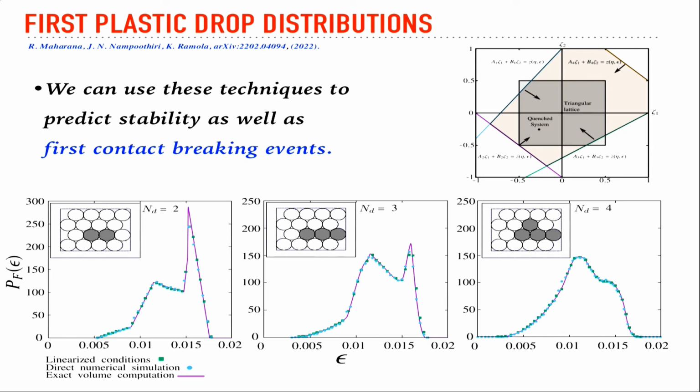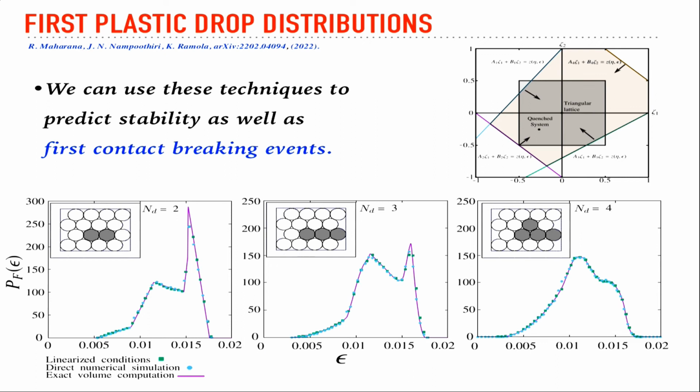As you increase polydispersity, you get a larger distribution here. This is more like some activity in the system, not fracture as such. If I shear a glassy material, things slip. Is this indicative of that, or of the system failing? This does look like a system-spanning event, so it's not a localized event. But it would not be considered a failure in the sense of a fracture. I would expect that as you increase the polydispersity, the distribution of when this fracture occurs would also increase, and the scaling can be extracted from these methods, although the exact distributions will be very hard.